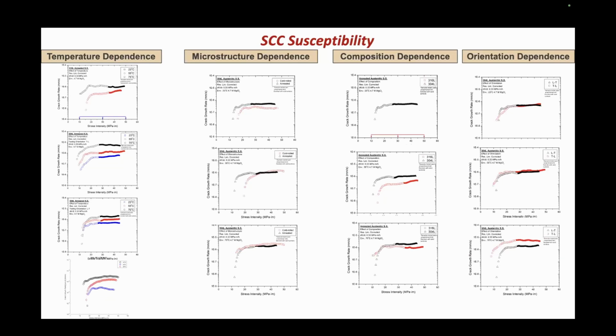We've done temperature dependence, microstructure dependence, which is going to be our 304L cold rolled versus our 304L annealed. And then we also have done composition dependence, so 316 versus 304 annealed, as well as orientation dependence. The plate that we have of 304L annealed has ferrite stringers in it. This was provided to us by Sandia, and so we wanted to see the effect of if we were cracking along the ferrite stringers or cracking through them for orientation.